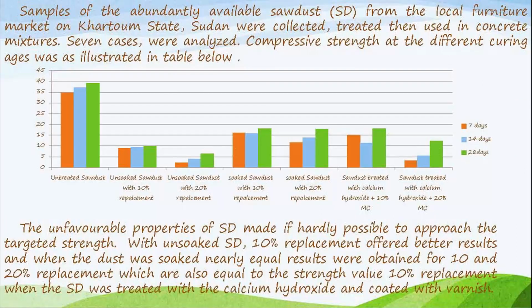The sample of sawdust was from the local furniture market in Khartoum state. Then we collected the treated sawdust and used it in the concrete mix, seven cases. We conducted the compressive strength for the seven trials. We have some positive results for the treatment for using sawdust as replacement for fine aggregate.